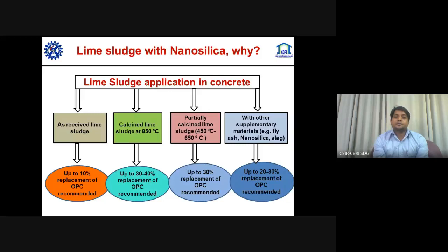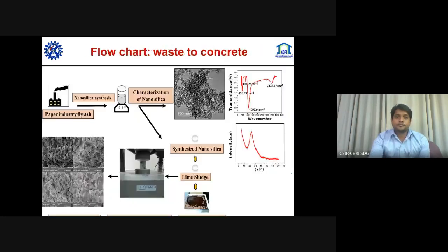And the third point, when we partially calcine lime sludge at 450 to 650 degrees C, we can further use up to 30% replacement of OPC, and I will take it further. And when we use lime sludge with nanosilica or other supplementary pozzolanic materials, it can replace up to 30% of OPC.